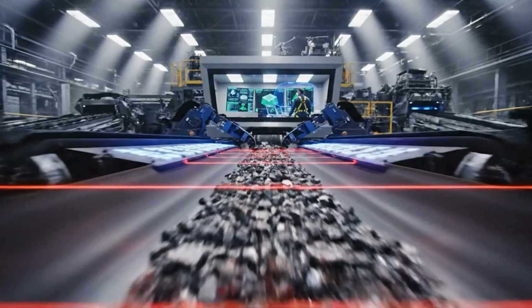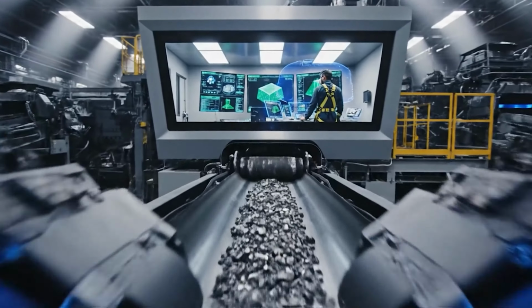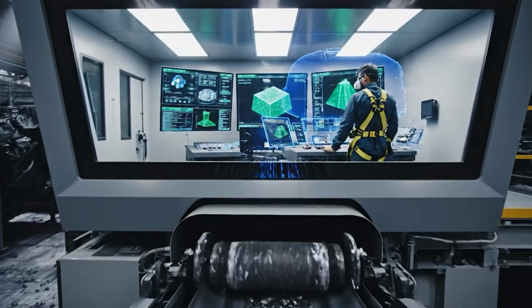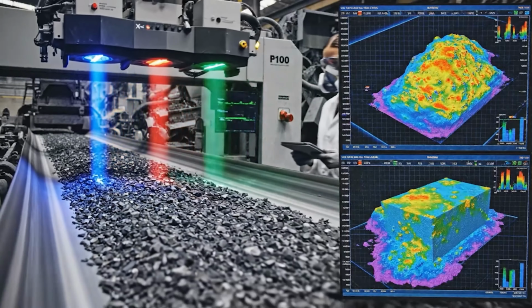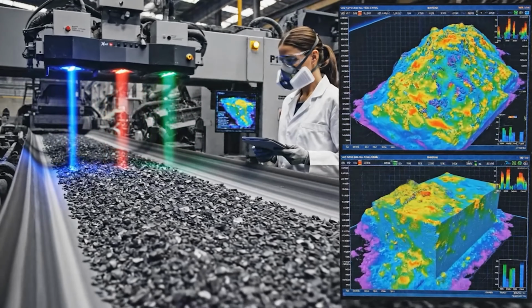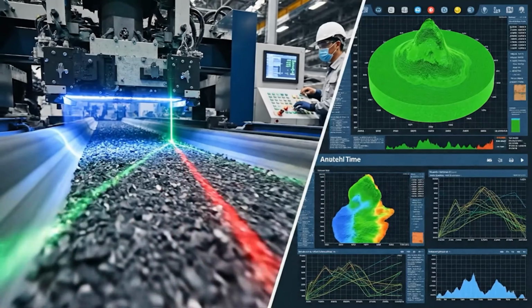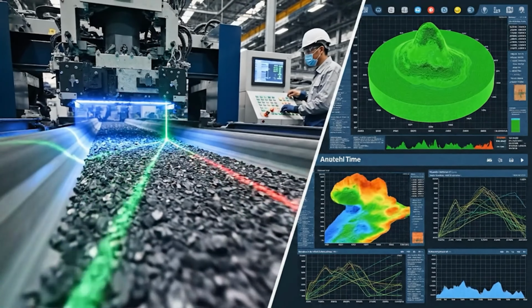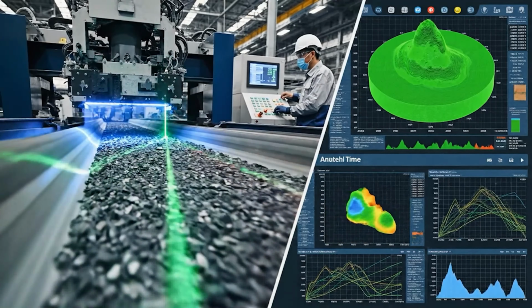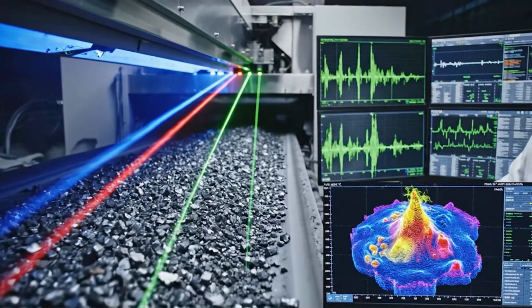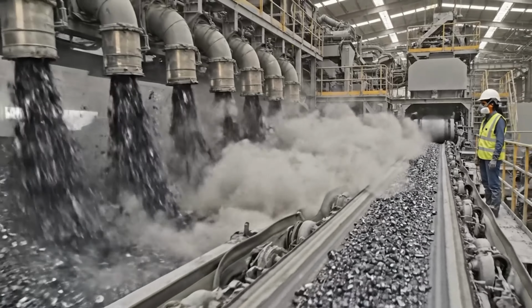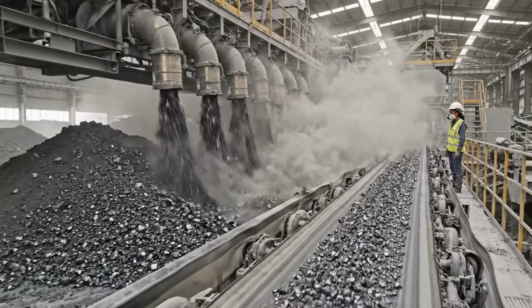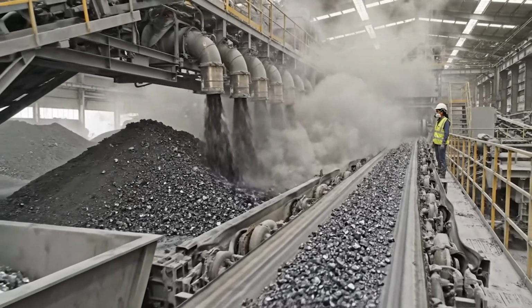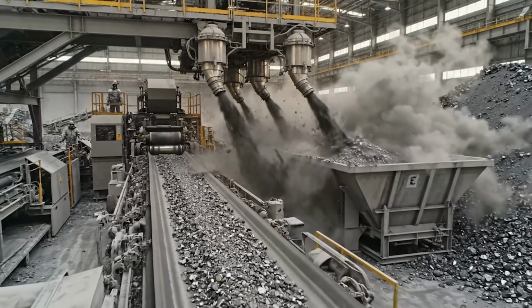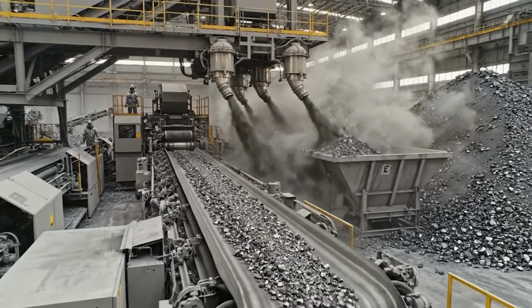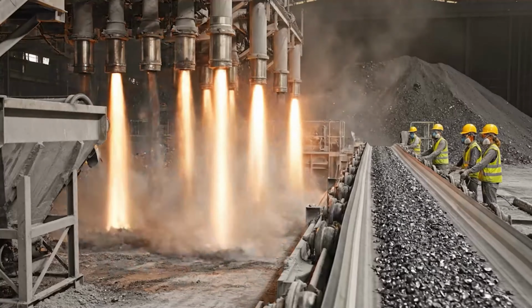Before chemical extraction, modern operations add an intelligent sorting step using the crushed material. As the ground ore travels on conveyor belts, high-tech sensors scan every piece. X-ray fluorescence detects metal content. Near-infrared spectroscopy identifies mineral types. 3D laser scanning measures density. Computer systems analyze thousands of particles per second. Pneumatic ejectors blast waste material off the belt at speeds up to 5 meters per second. You can hear the rapid-fire whoosh, whoosh, whoosh.